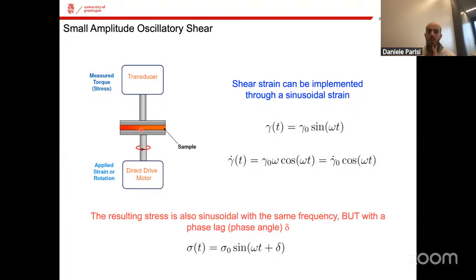The shear deformation can be provided in two ways. Either the motor provides a steady rotation with a constant speed that, of course, can vary, or you can have an oscillatory deformation, where you have a certain amplitude and a certain frequency. Usually this setup is called a strain controlled rheometer, because the rheometer can control the strain, which is typically indicated with the Greek letter gamma. Basically we have the strain amplitude, the amplitude of the deformation that we apply, times a sinusoidal function, which depends on a certain frequency.